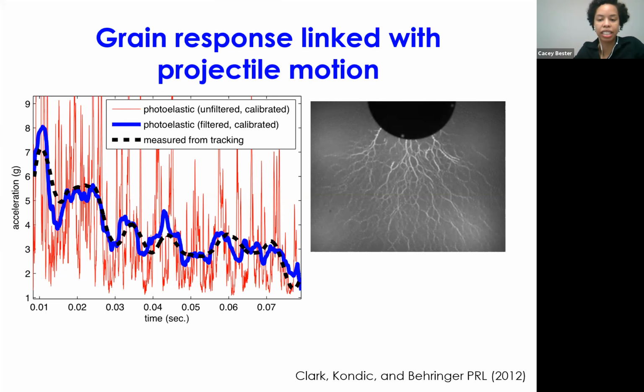So this gives us insight to show the connection between our force chain propagation as observed in the photoelastic measurements with the drag force fluctuations that we determine by measuring the projectile's trajectory, and shows that those fluctuations are intrinsic to granular impact. As you all pointed out, it connects nicely with the discrete nature of the forming and breaking of force chains that is exhibited in our system.